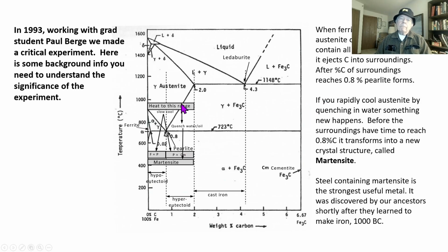Now, suppose that instead of slow cooling, you quench. This changes the big picture completely. Quenching does not allow enough time for the carbon to redistribute itself when you cross down to temperatures of about, actually it should be a little lower than that. Martensite starts to form, usually down around here. So if you quench fast enough, you'll get martensite forming down there. And before the surroundings of the areas have time to reach equilibrium percent carbon, it transforms into this new crystal structure called martensite.